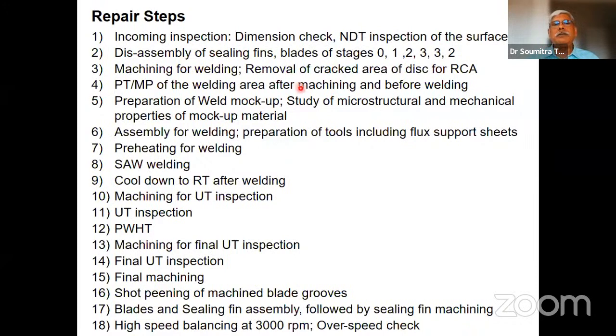So if you look at the repair steps, there's a large number. Of particular importance is removal of the cracked area and doing a root cause analysis of the failure. Why did the cracking take place at all? So that you know that there was no inherent, large-scale defect in the microstructure of the rotor, so that another failure does not take place in another place in the days to come after you have repaired and refurbished and put it back into operation.